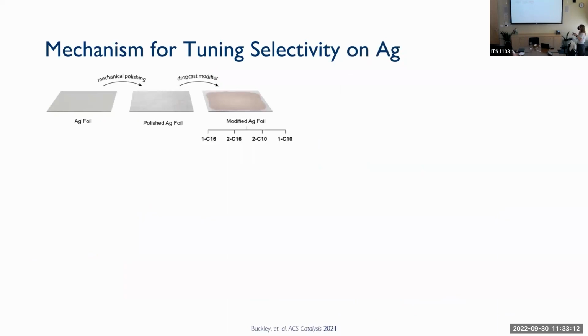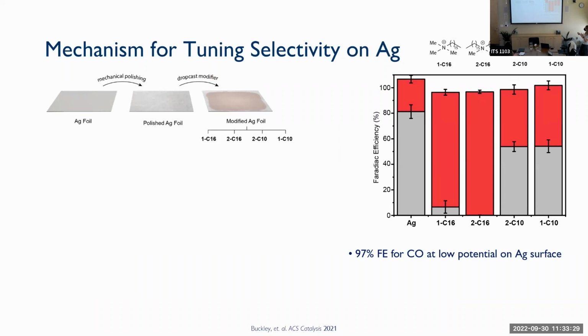We looked at water. Another thing that we looked at is CO2. And we did that by looking at silver. I told you that silver gives only CO basically, and so this is a much simpler example. We still looked at substituted ammonium salts, and what we found was that, so this is the class of the ammonium salts that we use, with one C16 alkyl chain, two C16, two C10 and one C10, and you can see that when you have two C16 chains, you basically become selective for carbon monoxide. Sorry, this is gray hydrogen, and this is just unfunctionalized silver. You see that you go from 80% selectivity for hydrogen to almost 99% for CO. In this case, the total Faradaic efficiency was 97% for CO. So we were able to take silver and make it really selective and low overpotential for CO.